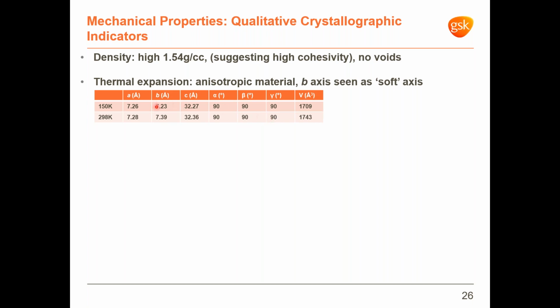In this case, we can, for example, observe a very anisotropic behavior, as most of the expansion happens along the crystallographic b-axis, suggesting the b-axis direction as the most compliant one.